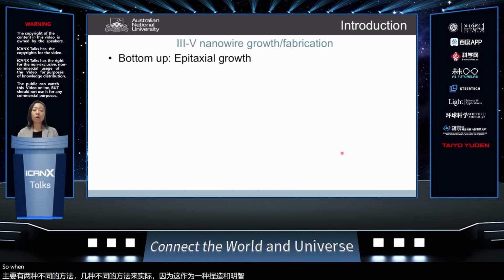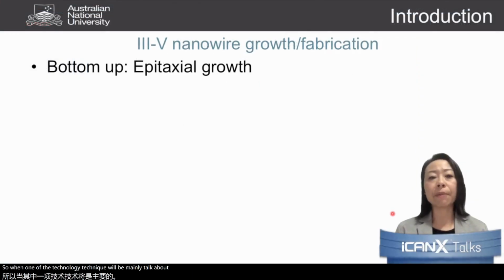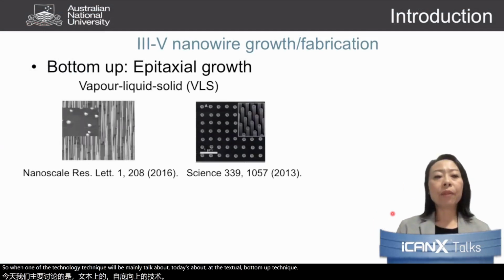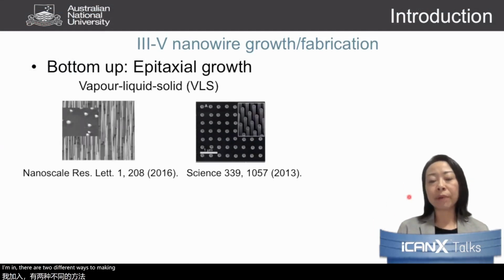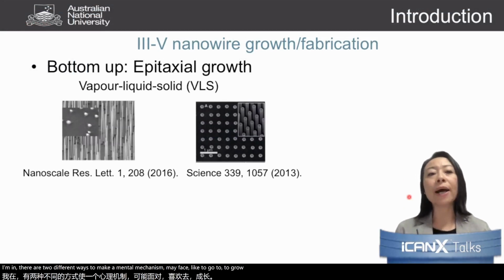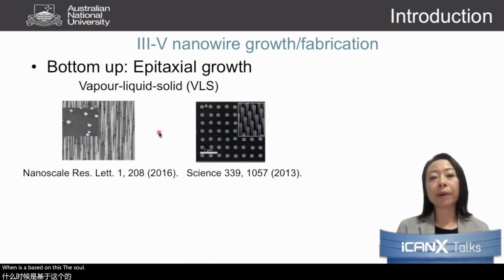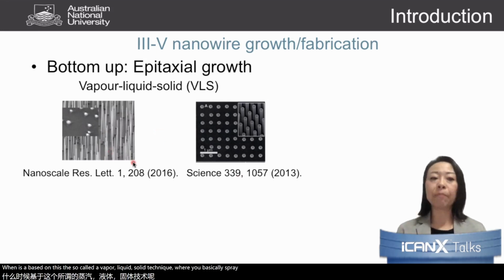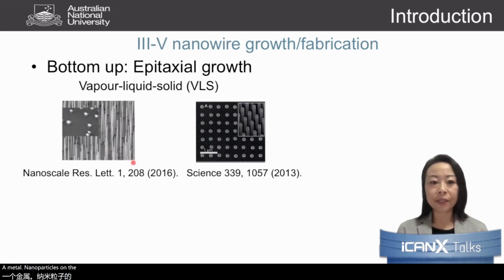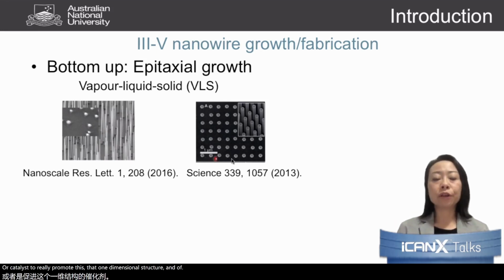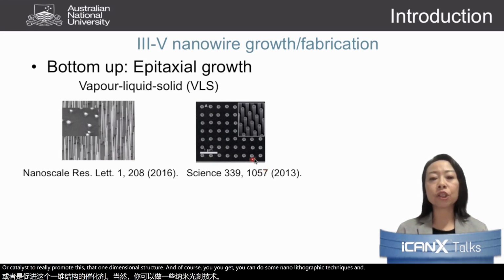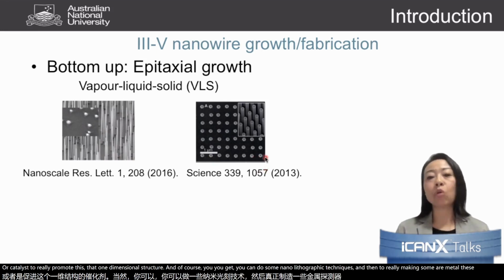There are a few different ways to synthesize or fabricate nanowires. One of the techniques I will mainly talk about today is the epitaxial bottom-up technique. There are two different mechanisms to grow nanowires. One is based on the so-called vapor-liquid-solid technique, where you spray some metal nanoparticles on the surface of your substrate, and these metal nanoparticles become a little seed or catalyst to promote this one-dimensional structure. And of course, you can use some nanolithography technique to make metal discs, such as gold discs, on the substrate.